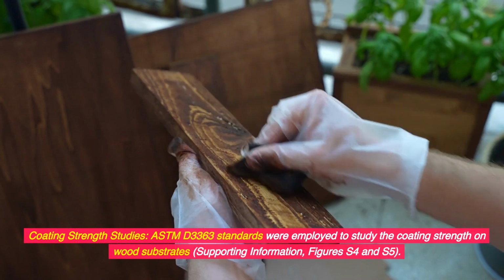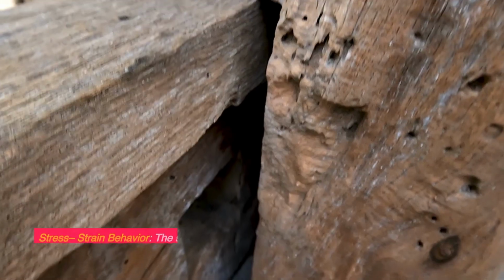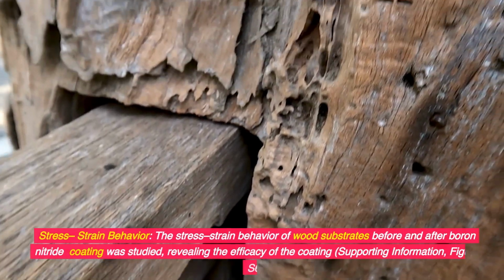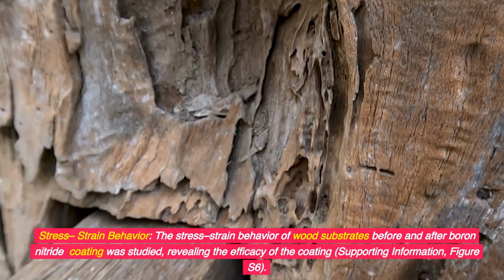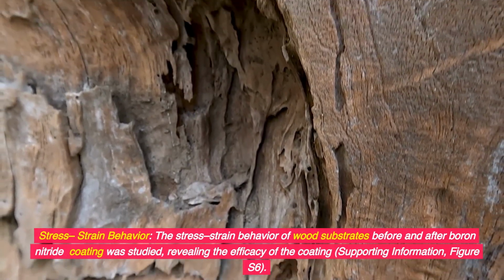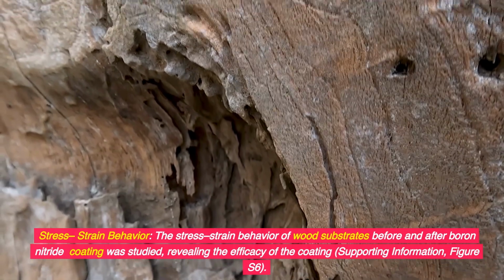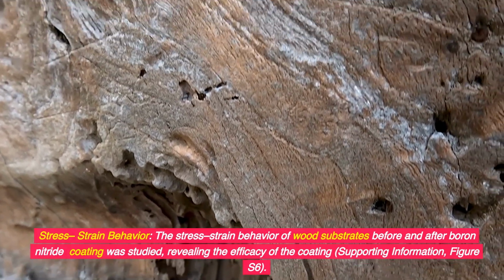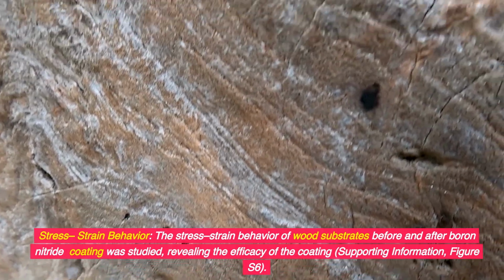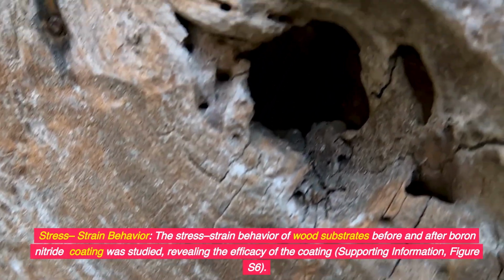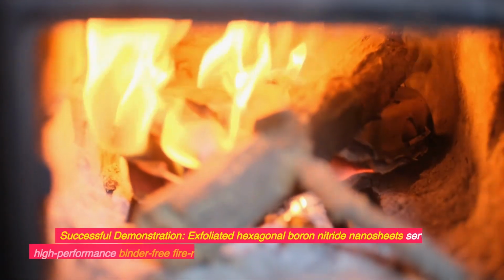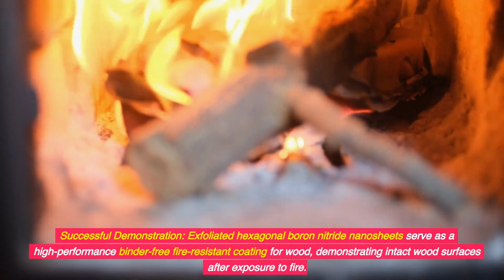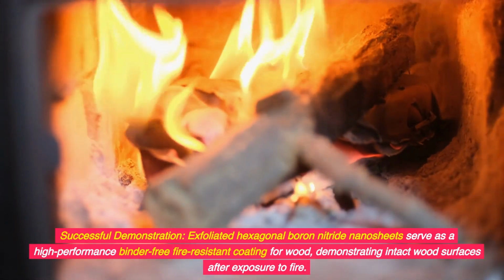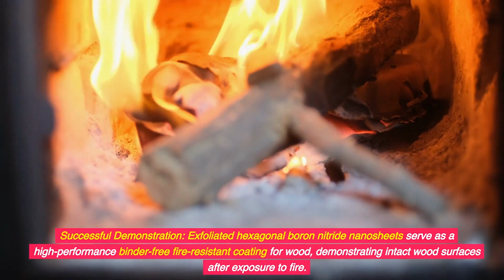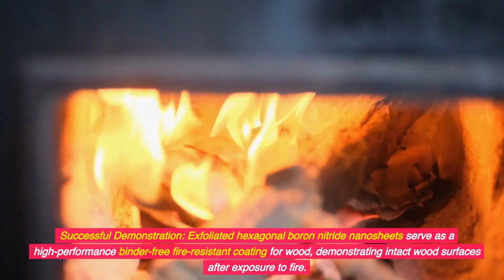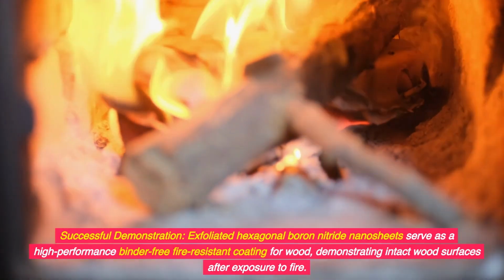supporting information figures S4 and S5. Stress-strain behavior: the stress-strain behavior of wood substrates before and after boron nitride coating was studied, revealing the efficacy of the coating, supporting information Figure S6. Successful demonstration: exfoliated hexagonal boron nitride nanosheets serve as a high-performance, binder-free, fire-resistant coating for wood, demonstrating intact wood surfaces after exposure to fire.